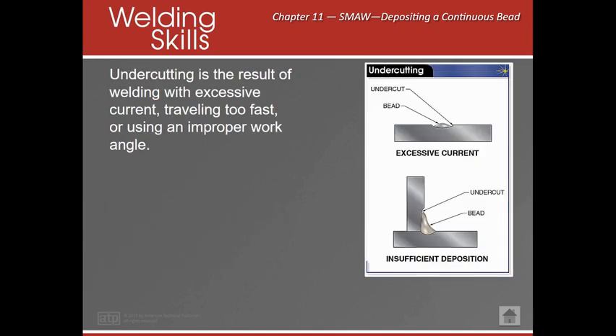Undercut is the result of welding with excess current or traveling too fast or the use of an improper work angle. So if you have something more than 15 degrees travel angle, and you have, let's say, less than 90-degree work angle, okay, you're putting more heat into one spot on that particular piece of material, and what's going to happen is you're taking away that base material, but you're putting that filler material in a different location because your work angle and your travel angle is off.